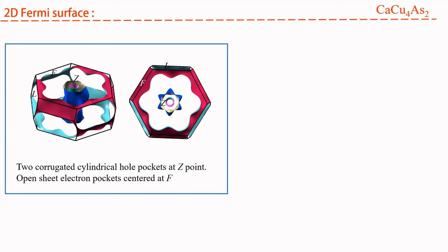Calcium copper four arsenic two has 2D open Fermi surface. It has two corrugated cylindrical hole pockets at Z point and open electron pocket centered at F. This 2D nature is also observed in electrical transport measurement.